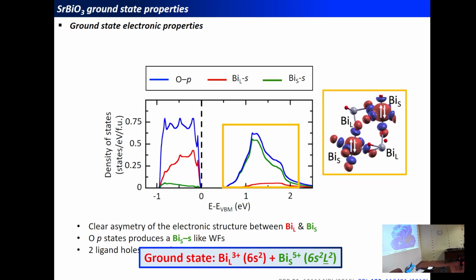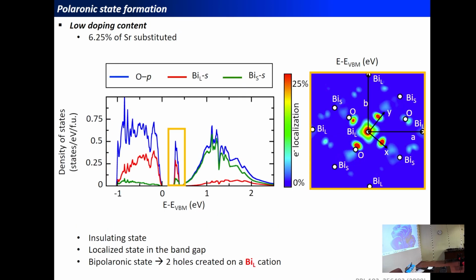So now that we have understood the electronic structure of our strontium bismuthate, we can start to dope the material and see what happens when we put holes in the system. The idea there is to substitute partly the strontium cation by a monovalent potassium cation. If we do that at low doping content, at 6.25% of substitution, we observe that we have an insulating material with a localized state in the band gap.